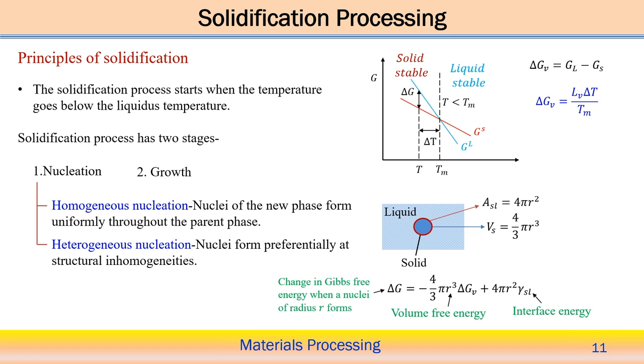Solidification starts when the temperature goes below the liquidus temperature, because going below it means some degree of undercooling is available to the system. Here delta T, the degree of undercooling, is available for the system, and this is the driving force for the solidification. Now, the phase changes from liquid to solid; below the melting point the solid is the stable phase, and above the melting point temperature the liquid is the stable phase. And here we see the volume free energy change, the Gibbs free energy delta GV.